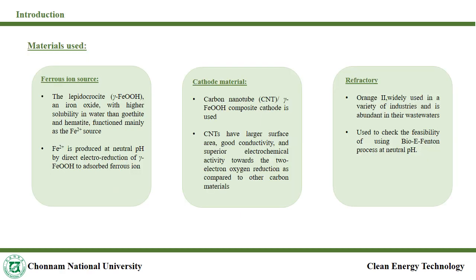The main components used are a carbon nanotube and lepidocrocite composite electrode and orange 2 dye. Lepidocrocite is a ferrous ion source and has higher solubility in water than goethite and hematite. Ferrous ions are produced at neutral pH using lepidocrocite. Carbon nanotubes have a larger surface area, good conductivity, and superior electrochemical activity. Orange 2 dye is used as a refractory to check the feasibility of the process, and it is abundant in the wastewater of most industries.